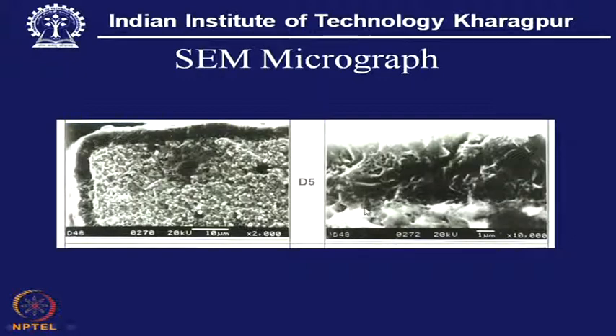Now, what we see here is actually the interface, where the picture has been taken. So, this is the interface, and from this point, that is the coating. So, we can assess the coating thickness, and with proper clarity of the picture we can also see the morphology of the coating. It started from this surface, that was the interface, and then we have some seeds also.